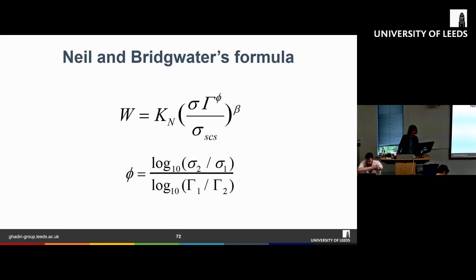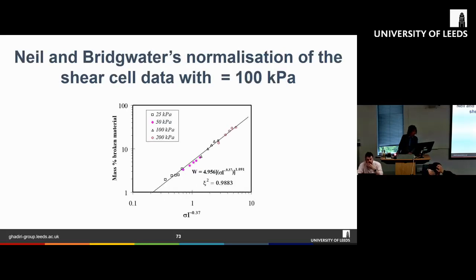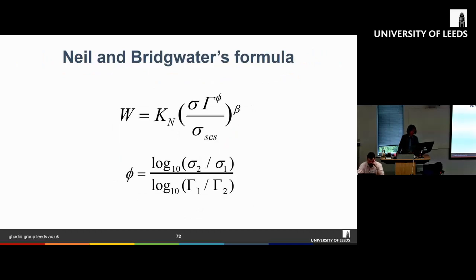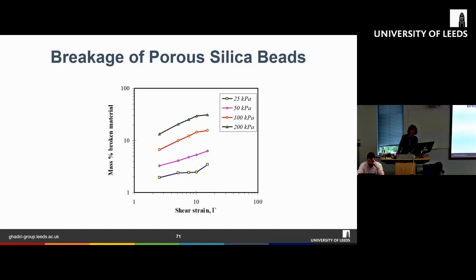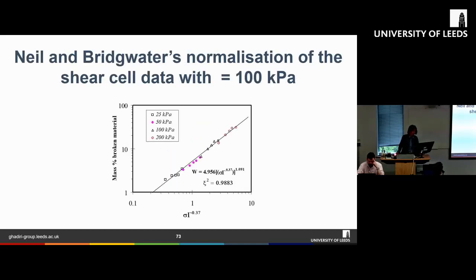And this is just correlations of how we can describe the breakage under shear deformation. Here is the equation, and I won't go through it in detail. Here is Neil and Bridgewater's normalization of the shear cell data. If you apply this equation, you can essentially unify this data into a straight line like this, which gives us a measure of the breakage of the particles. In other words, it gives us some sort of predictive capability on how the particle will break under shear deformation.